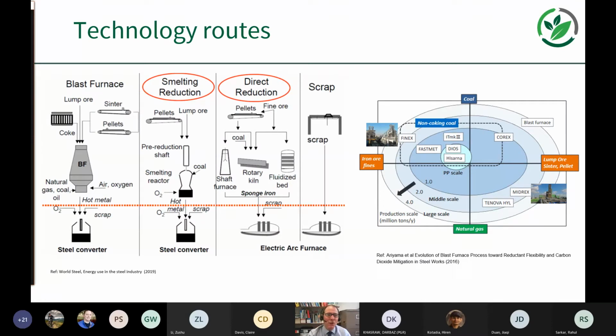So just going through the technology routes quickly again. We've got this blast furnace, and of course this high energy requirement and the CO2 emissions is a carbon-based thermochemical process. And it requires processing these raw materials quite significantly before we charge them to the furnace, even before we start to use them. And of course, that results in this energy intensity. Then we have smelting reduction. Now, that hasn't got the pre-processing of producing coke and producing agglomerated fines in the form of sinter. And that also produces, like the blast furnace, a liquid hot metal product, which tends to go into a basic oxygen furnace.